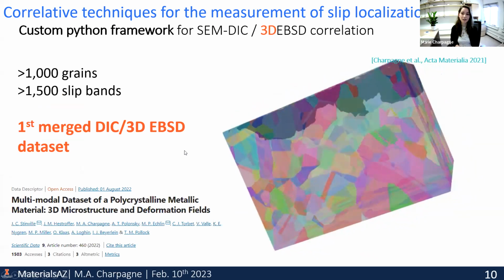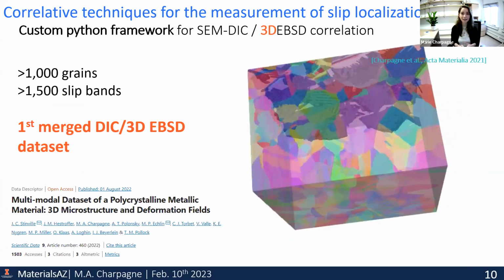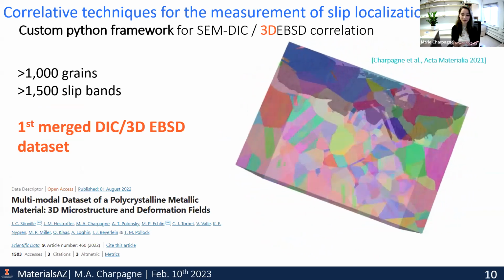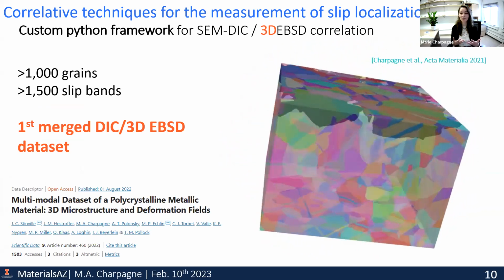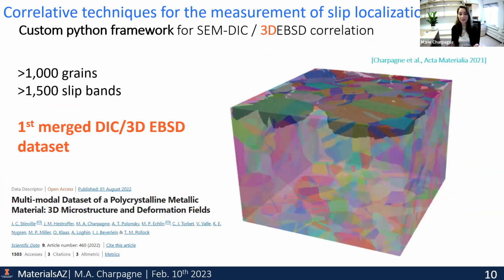So going back to our idea of mapping the microstructure, well, we can now, using this idea that you can extract the fatigue strengths of any material without actually doing a fatigue test, by just doing one cycle in tension, well, we're now down to trying to understand how the slip bands form as a function of microstructure. And we did that in a bunch of materials in 2 dimensions and found some correlation. But we thought that, since the dislocations come from the bulk of the material, it would be more insightful to actually collect the 3D microstructure of the material and map the slip bands in 3 dimensions.